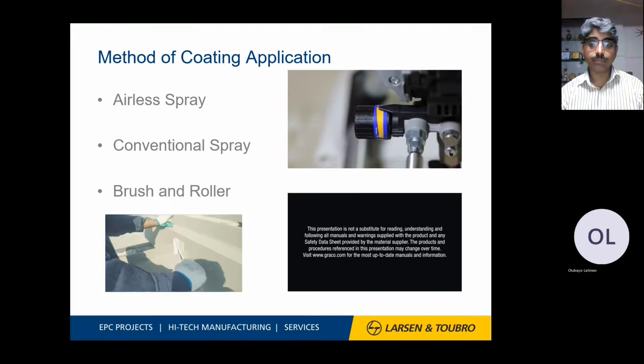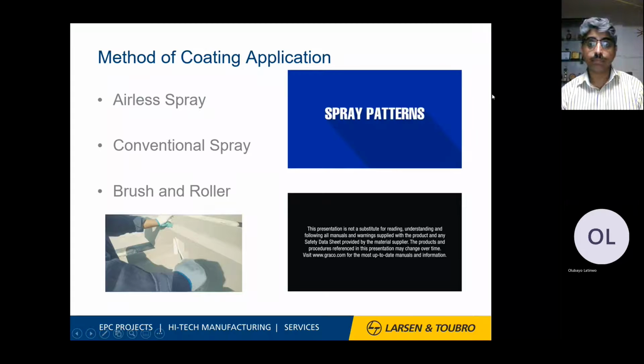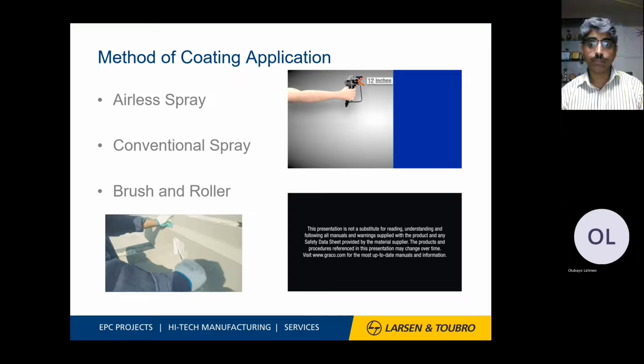If you're at the maximum pressure setting and the spray pattern is still not suitable, a smaller tip hole size should be used or your material may need to be thinned. Follow the instructions on the back of your material container under spraying applications. The gun should be held approximately 12 inches from the surface and aimed straight at the surface. While moving vertically or horizontally, the gun should remain at a consistent distance from the surface.